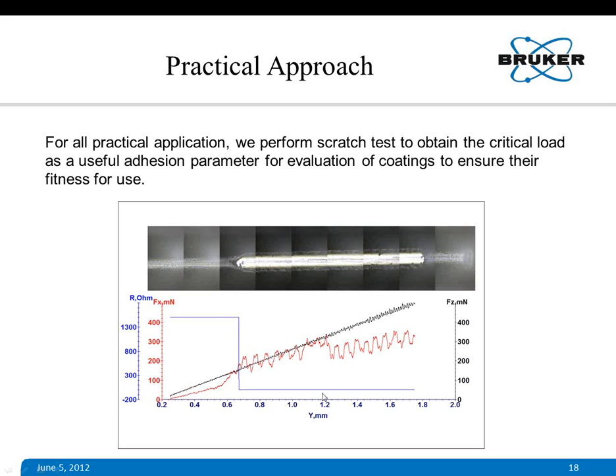The resistance drops to a very small value, and we know where it is failing. In this case, say for instance, R is changing, it dropped at this point, and also the tangential force, which is Fx, basically started becoming unstable at the point of failure. It changed abruptly.